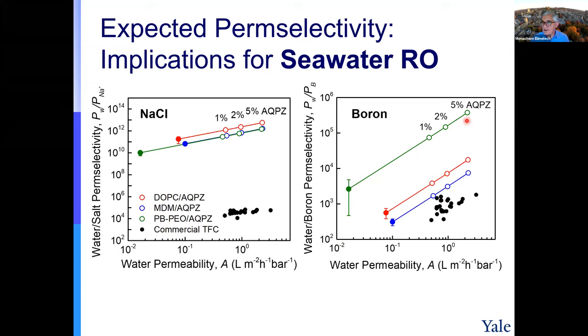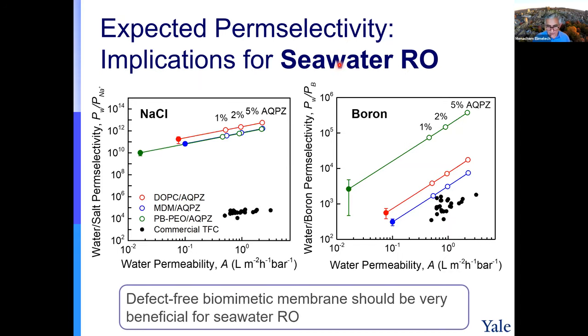And as you see, the boron will be, again, not many orders of magnitude, but at least 2 to 3 orders of magnitude more so. It means the rejection will go from 75 to about 98%, which means that you will not need additional passes for reverse osmosis. So all in all, for seawater desalination, they work well.